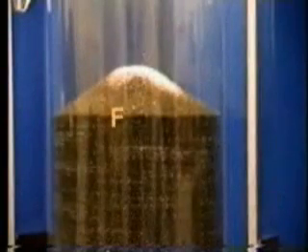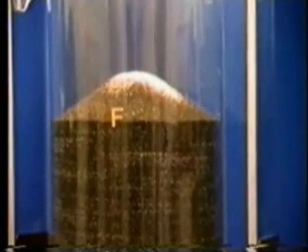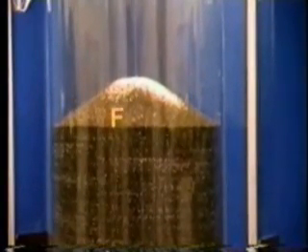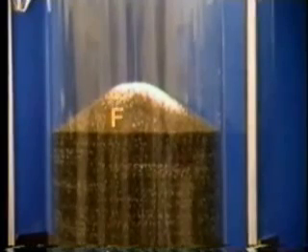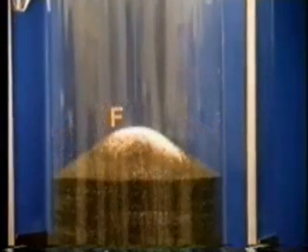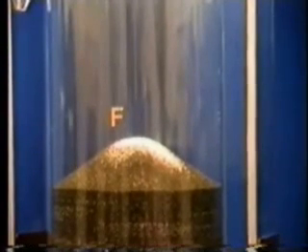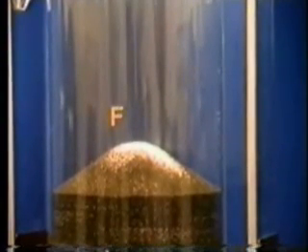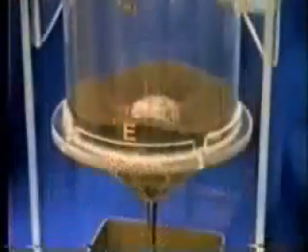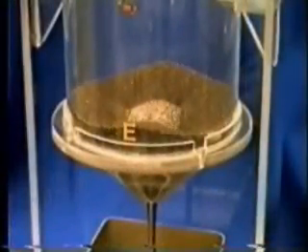The bottom gate is now opened and the sand exits the bin. The sand dome formed in the center of the bin does not immediately fold in. Instead, it rides down on top of the sand. This indicates the sand is feeding through all 4 openings in the inverted cone and going down level.